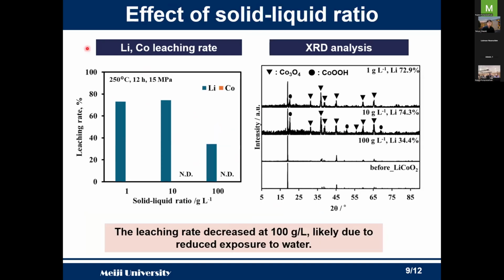Next is the effect of solid-liquid ratio. This graph also shows the effect of solid-liquid ratio. At 1 and 10 grams per liter, the leaching rate was almost the same level, but at 100 grams per liter, the leaching rate decreased.